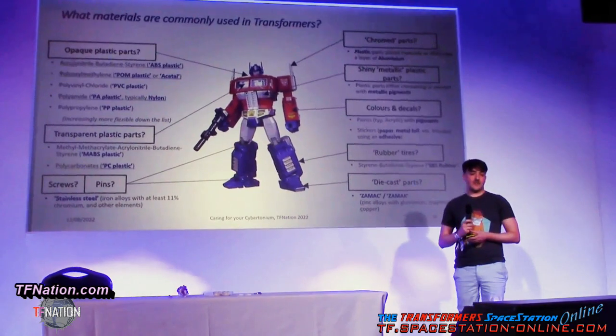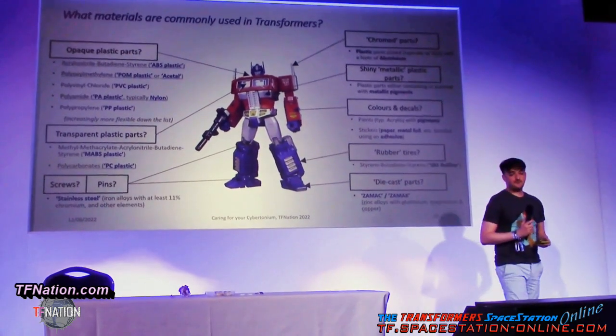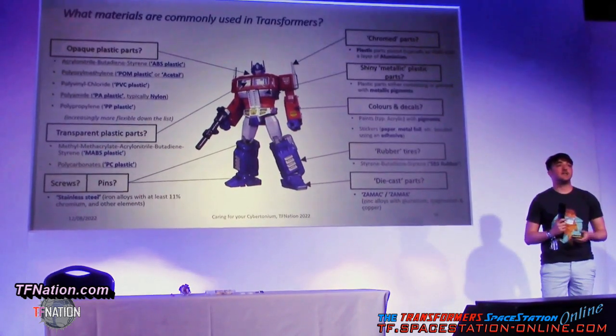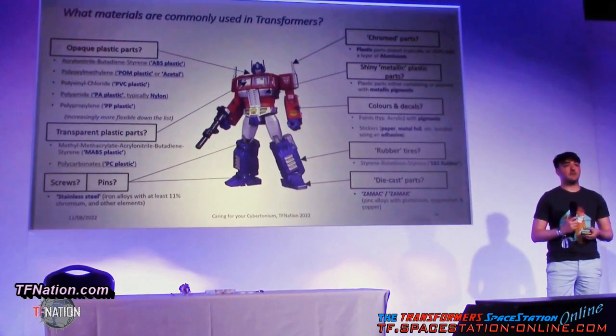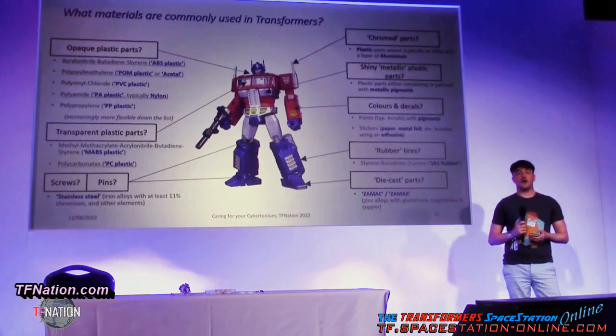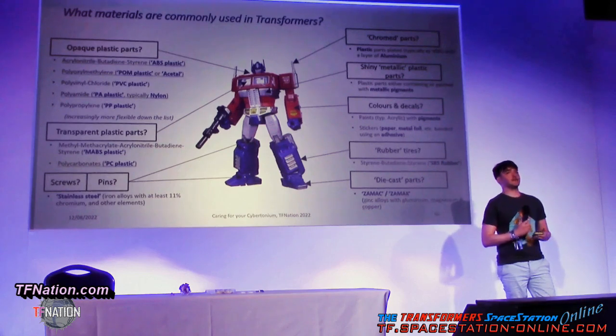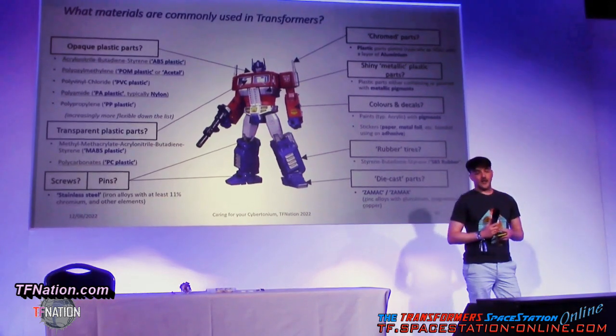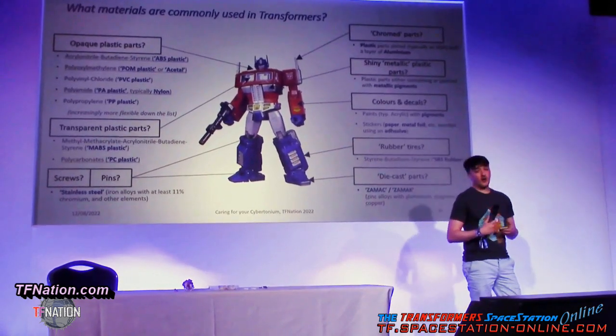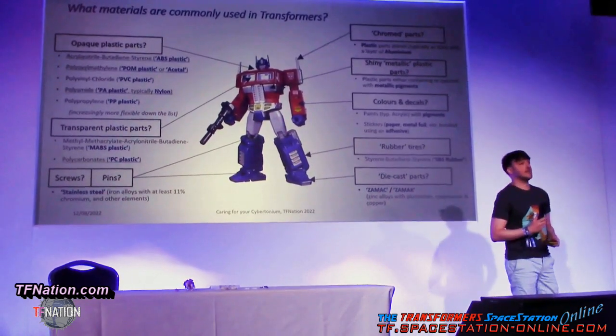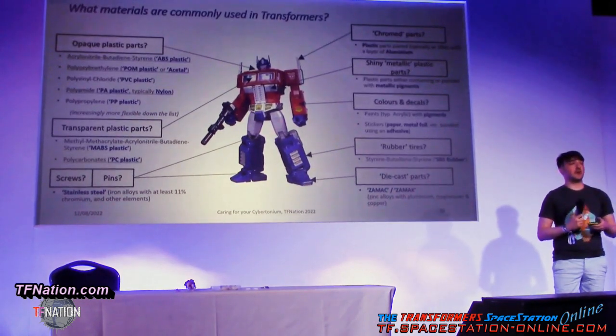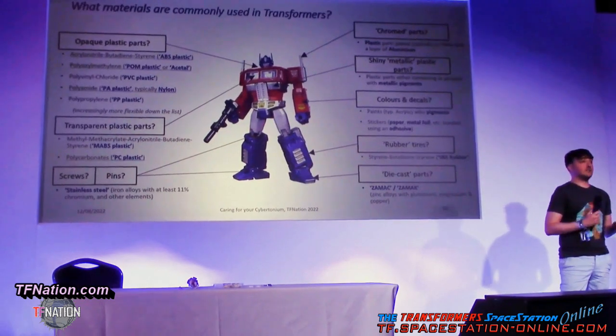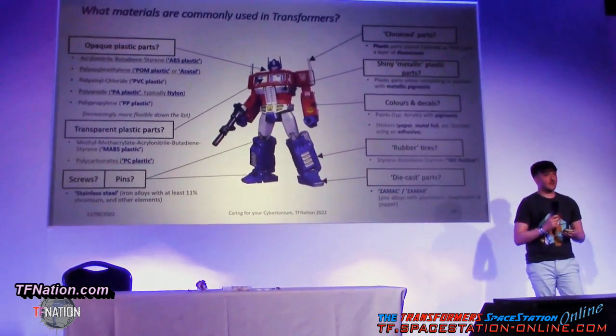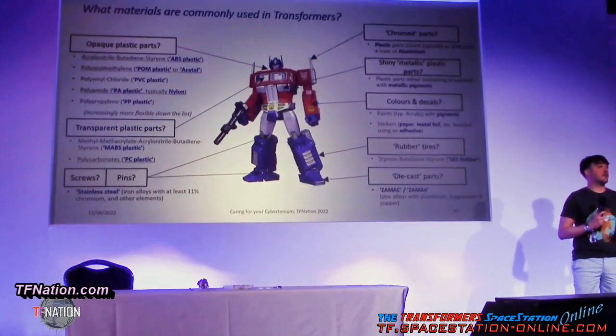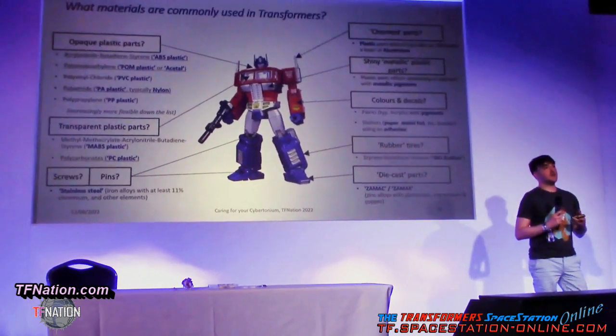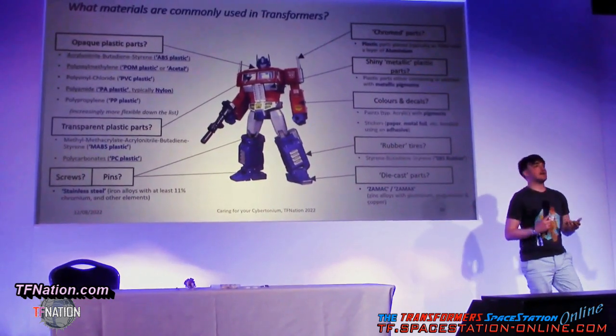Shiny metallic parts. So these are generally one of two things. Either it is plastic which contains metallic pigments, so again, something like aluminium, in very small amounts. Or it's plastic which is painted and the paint contains metallic pigments. The effect of the paints or the plastic is really dependent on the size of the pigment. So it can vary from, I believe, down to about 70 microns, a micron being 1,000th of a millimeter, all the way up to about 0.7 millimeter. And the finer it is, the more of a sheen it gives, and the larger it is, the more of a sparkly effect it gives.